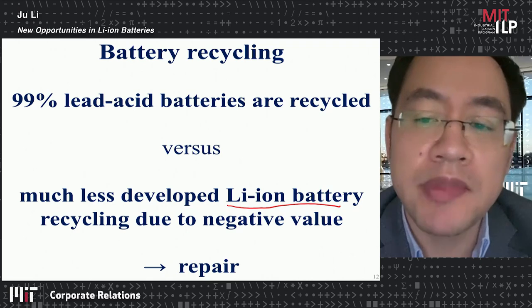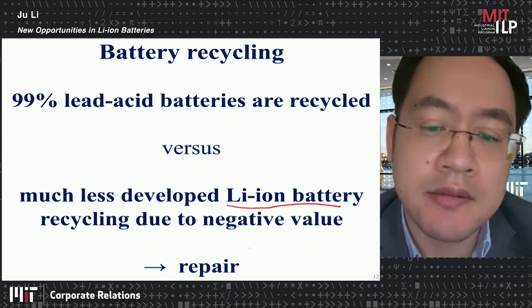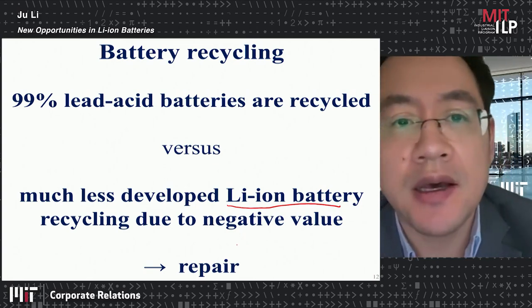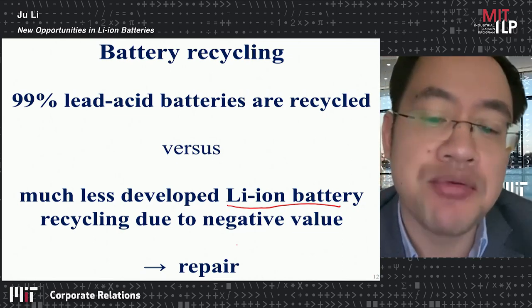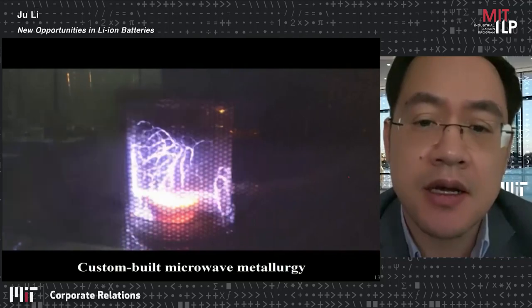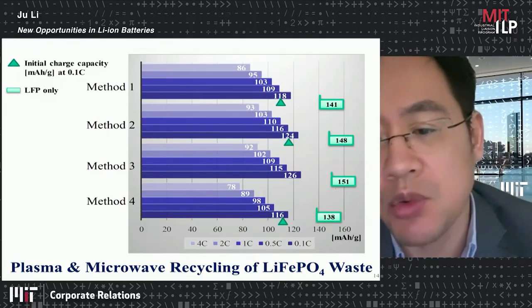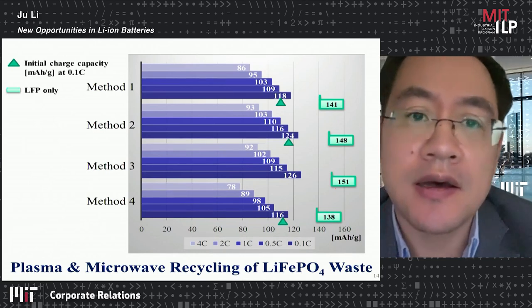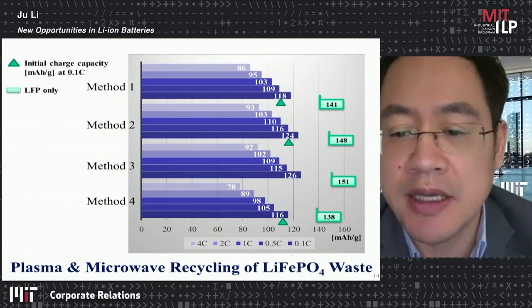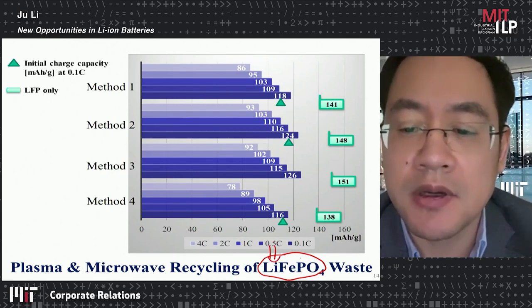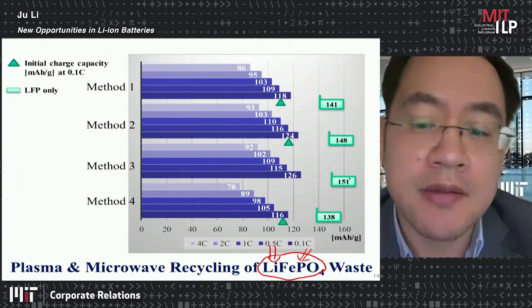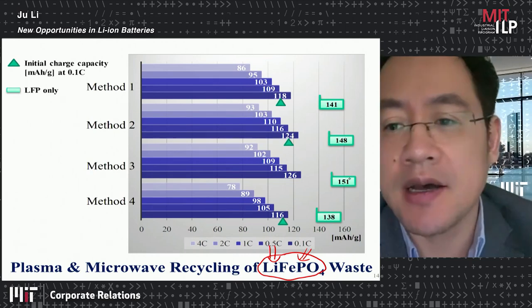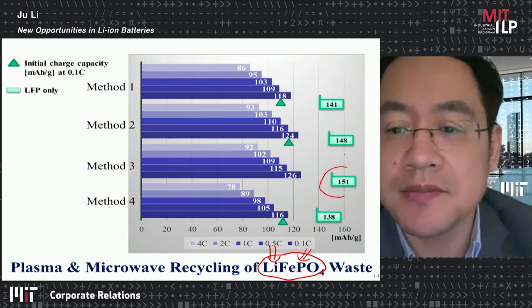Recycling is a huge problem, and what we have been working on are techniques to look at direct repair. So instead of getting the cobalt and nickel and lithium out separately, we try to use microwave methods. This is a microwave system developed in the lab to look at low energy, low environmental impact recycling of the cathode material, especially lithium iron phosphate, where we can recover the lithium and we don't go back to square one, and we can replenish the lithium resource a little bit. Depending on the different methods, we can get up to 150 milliampere hour per gram, if you look at just the active material.